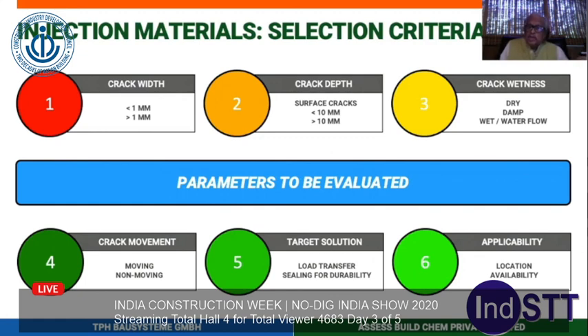It will totally depend upon whether the crack is dry or whether it is damp or whether water is coming out of it. If the water is coming out of the crack, you have to really stop that incoming water by putting a pressure with your machines to push back that water and the injection resin to reach the place where it is designed to reach. The crack movements, whether the cracks are moving or they are not moving.